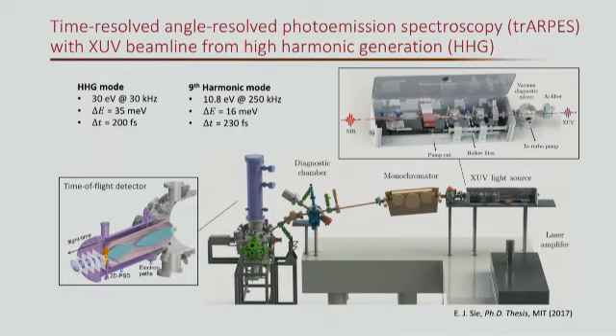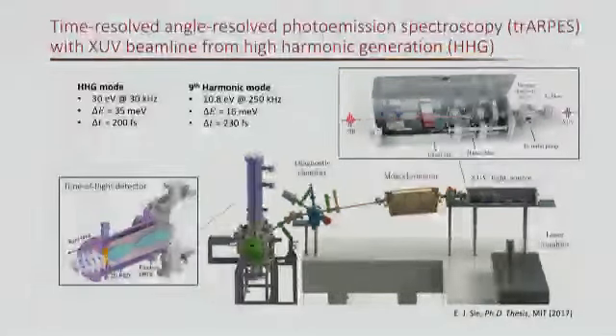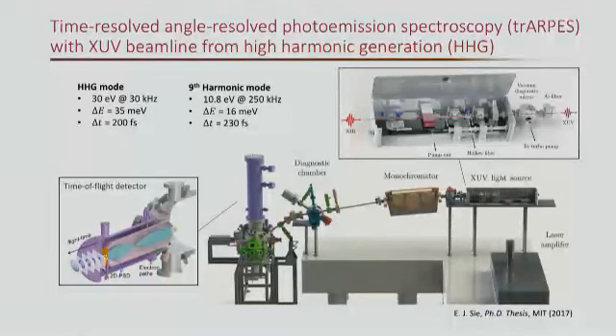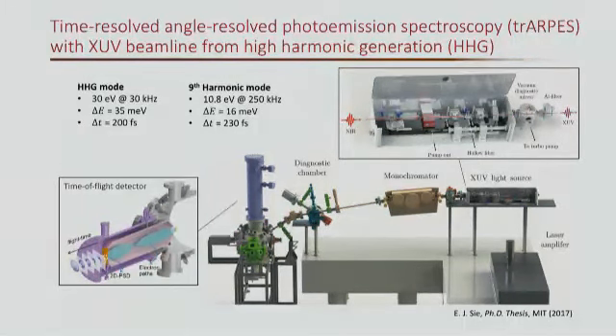Another mode of operation, which is used in the current study I'm going to present, is the ninth harmonic mode, where we first send the third harmonic of a near-infrared laser to this hollow fiber, and it generates another third harmonic. So a third of the third harmonic is basically the ninth harmonic, which can give us up to 10.8 eV. I want to emphasize that here we can actually get down to below 20 meV resolution, which is very close to the Heisenberg limit, considering the time resolution is about 230 femtoseconds.